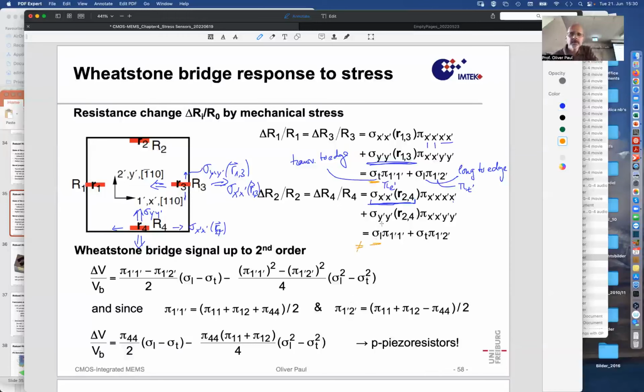And the stress in the y direction here at this location is the same as the x stress at this location. So this stress here we call the y. This y normal stress in y direction is what we called sigma transverse up here. It's the same as the sigma xx up here. So this is how these two responses come about, and you see that the two resistor pairs have different relative resistance changes because the piezoresistive coefficients are multiplied, well, with switched stresses in both cases because of this 90-degree rotation.